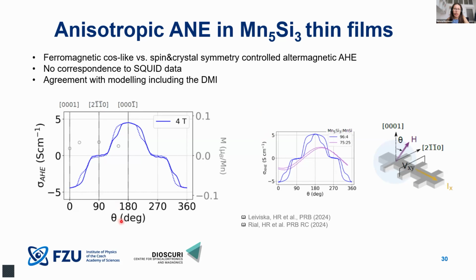So here is a rotation of the external magnetic field, which sets the spins to different orientations. There are some plateaus where the anomalous Hall effect is not allowed, and then there are regions where it is allowed, but it's not a smooth cosine-like variation, which we would expect for a ferromagnet-like signal. Also, importantly, when we lower the crystal quality, with Mn5Si3 of, let's say, polycrystalline quality, we do have some Hall effect. However, it has this cosine-like smooth variation. So it's yet another evidence that the anomalous Hall effect and its anisotropy depend on the high crystalline quality.